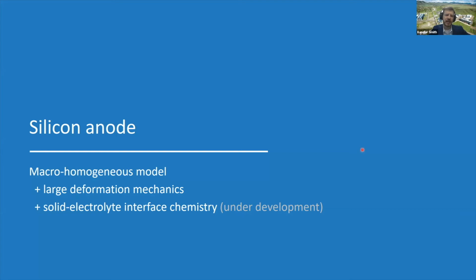And for the silicon anode, we're working with a consortium of different labs under two different programs, the Silicon Deep Dive and also the SEISTA, SEI-STA is the acronym, understanding the side reactions that occur on the silicon surface. So definitely mechanical deformation is a problem for silicon, but also the kinetics of these side reactions, the SEI formation, is perhaps even a larger problem. It's a very reactive system.